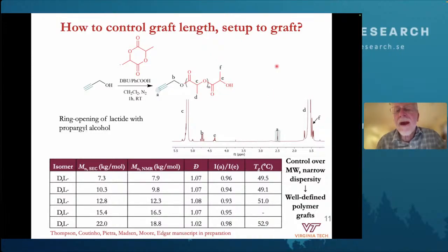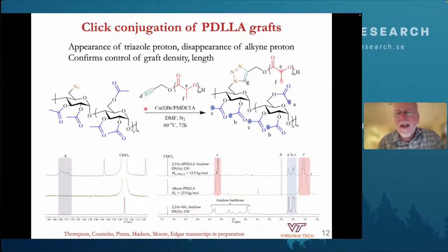Now we have a branch of controlled length with an entity on its end that enables us to click it onto the polysaccharide. And sure enough, that click chemistry worked well. We have this triazole linker between the starch, the amylose acetate, and the PLA side chain, and many different ways that we proved we actually had the material we claimed, including DOSY spectroscopy, where you can see we don't just have a mixture of the two polymers—we, in fact, have a block copolymer.